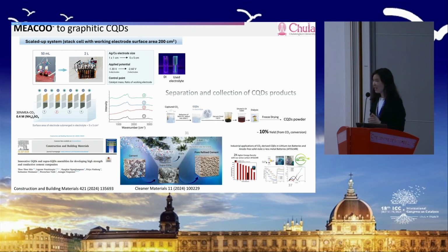Okay. The system is simple enough to be scaled up. We scale up our system from 50 milliliters to a 2 liter system with a stack of electrode cells. And we were able to obtain a lot of carbon quantum dots in the solution and also on our electrodes. After repeated use, making more and more carbon, we can separate our carbon product out by just simple dialysis and then freeze drying.